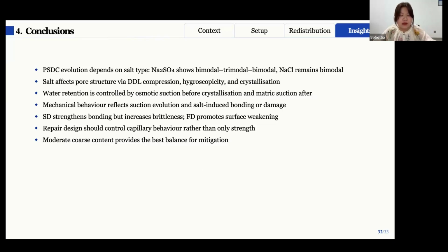So to wrap up, we have seen that salt, water, and microstructure are strongly interconnected. At the pore scale, different salts lead to very different microstructure evolution. These differences then control how water is retained and redistributed, and eventually how the material responds mechanically. What is particularly important is that these processes are not independent. The hydraulic behavior, the mechanical response, and the microstructure all evolve together during salt crystallization and dissolution.